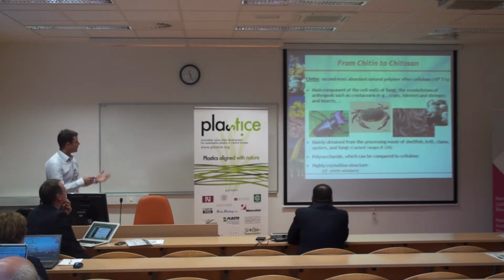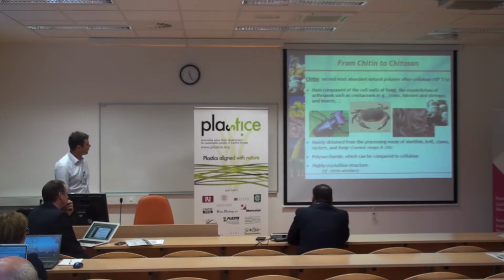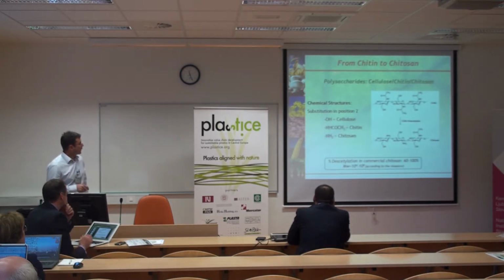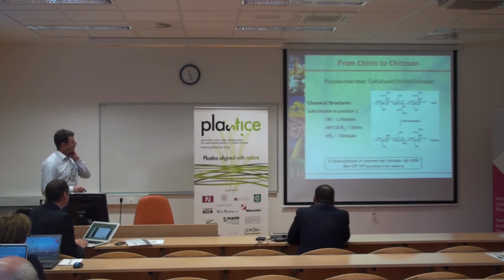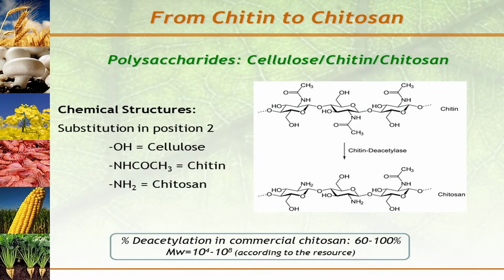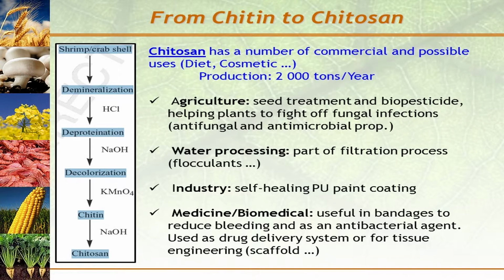So it's quite similar to cellulose for the plants. And it also has a highly crystalline structure. That's why we can recover chitin whiskers, which are the crystalline parts that can also be used as a nanocomposite filler in some cases. So chitosan is obtained by deacetylation of chitin, and typically for commercial chitosan the deacetylation degree is between 60 and 100%, usually between 90 and 100% being the most common values. So chitosan is produced at around 2,000 tons per year and has different commercial and possible uses.